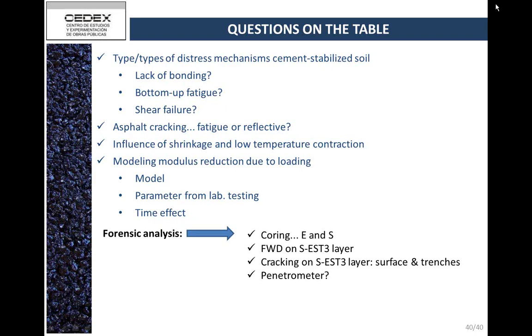When you have a complete lack of bond, you certainly can see that, because we've seen that type of thing here on pavements as thick as 10 inches on crushed granite bases. When we've had a complete loss of bond, you can actually see a change in the aggregate particles in the mix on the surface. Well, we do not have that here for sure. From the surface you cannot see any movement of the particles in the longitudinal direction. I am almost positive of that. But maybe, I don't know. Maybe if we have the bonding, it is not enough to mean a movement of the asphalt layer, at least here. I think, Fred, you can also see, I mean, you don't always have to see it.